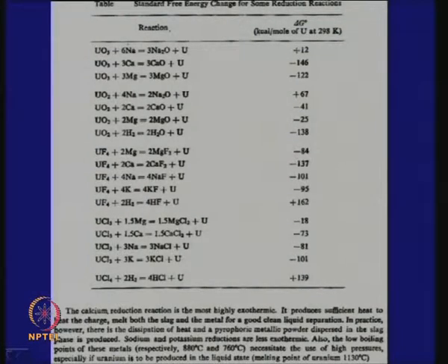So, we produce high carbon ferrochrome, but we could avoid having carbon in ferroalloys if we went for metallothermic reduction. Here also, if you have a pure oxide, we can reduce by sodium or calcium and produce the metal, no problem.